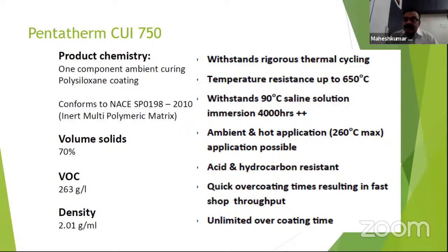We tested this polymer up to the 650 degrees C range. We tested this material in 90 degrees C saline solution conditions for 4,000 hours. We have tested for acid and hydrocarbon resistance, and we kept our VOC level below 263 grams per liter. When we made this polymer, we chose the other ingredients such as pigmentation, different types of extenders, and some special additives to give proper adhesion at high temperature also. We also ensured that this material will have a higher or unlimited overcoating time.